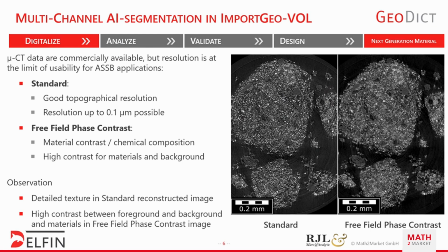First of all, the micro CT resolution is right on the edge of what you can use for this problem that we are facing here. And we needed a solid way to improve our image quality. Fortunately, RJL is able to provide us with two different reconstructions of the same scan. We have the standard scan, which gives a good topographical resolution, seen here on the left. And we have a free field phase contrast reconstruction of the same scan, which is basically giving us a better contrast between background and other components which we find in the solid state battery.